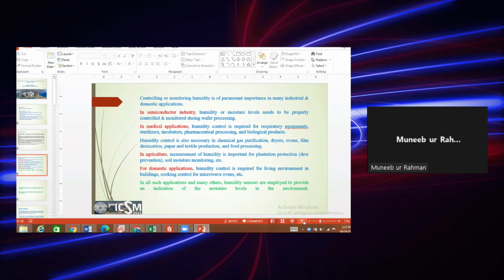The recovery and response time also depend on the material nature and material structure. Sometimes the material is hydrophobic and sometimes hydrophilic, so it depends on the surface of the material and its interaction. It also depends on the adsorption and chemisorption process of the material, and on the pores and the sizes of the pore channels. If we go into more detail, it also depends on the grain boundaries inside the material as well, and the defective nature of the material.